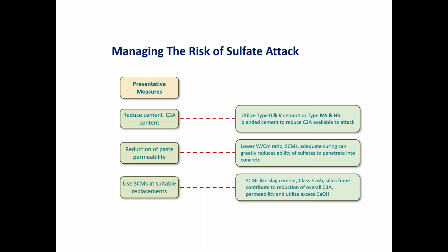Reduction of paste permeability. This is probably one of the things that everybody understands, and it translates to a lot of different problems in concrete. The more permeable the paste is, i.e. the more water to cement that was used, the higher the water cement ratio, the more opportunity there is for things that shouldn't be in concrete, that you don't want to get into hardened concrete, to get there. So managing water cement ratios, specifying proper water cement ratios, is very critical. And then the use of suitable replacements of SCMs. It's not just suitable amounts, it's also suitable SCMs. And as you'll see, not all supplementary cementitious materials are created equally. These include slag cement, fly ash, silica fume, and can even include metakaolin or calcined clays and other types of natural pozzolans.